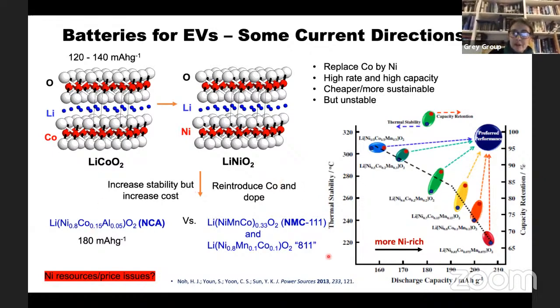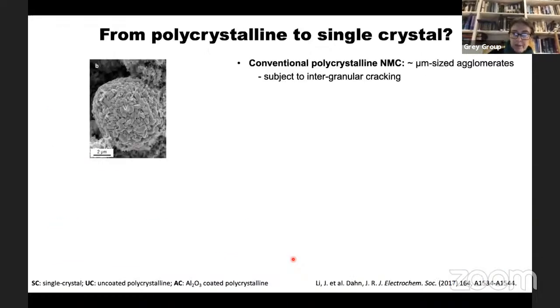And so what the field has come up with is this whole slew of different compounds where you take the cobalt or the nickel and then you mix in manganese 4+ to make it more stable. Manganese is a more abundant element. You put in aluminium to increase the stability. And as a result, this is the material that's in the current generations of cars. And this is the next generation material. It's so-called NMC, so nickel, manganese, cobalt, 811, where 8 stands for 80% nickel, 10% manganese, and 10% cobalt. And so this is the material that we work on to try and understand whether it's really fit for purpose and how it degrades and how to mitigate that.